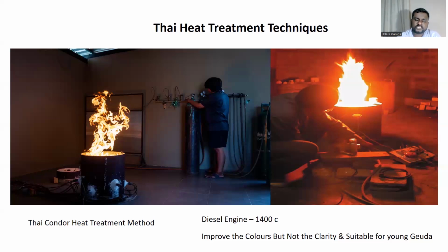So the thing is, sometimes even after burning in this type of Thai condor oven, you will not be able to get rid of the thick silky inclusions, rutile needles. So you will not be able to achieve the expected clarity if you burn gems in this type of Thai condor oven. Because this can hit up to 1400, but usually the rutile needles get 100% dissolved only after 1650. Even sometimes some thick Geuda stones we have to burn even up to 1850.